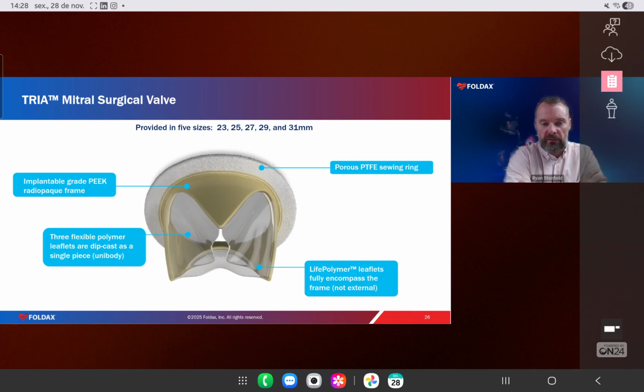And you'll see that here. The frame, like I mentioned before, is polyether ether ketone. It's been made radiopaque, so it can be seen under visualization while it's in the body. The 3 polymer leaflets are dip cast as a single piece. So this isn't taking a sheet of polymer and cutting out a leaflet and then bonding it on or suturing it on. These leaflets are all dip cast into place on this frame. And then that same material, that LifePolymer material, encompasses or encapsulates the PEEK frame as well. And then a porous sewing ring that's also polymer is sewn onto the PEEK frame. So you've got a full polymer valve here.